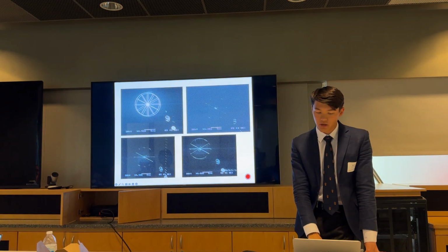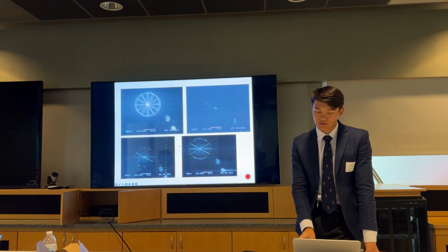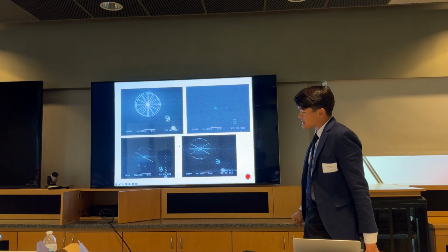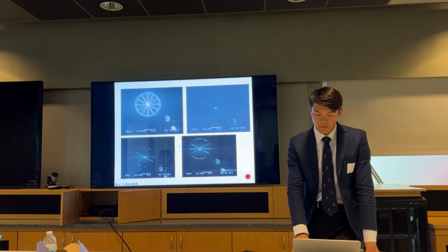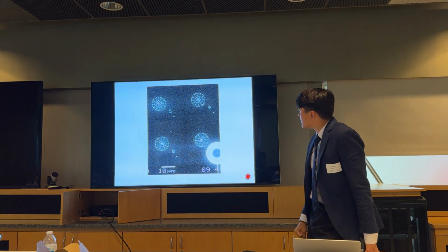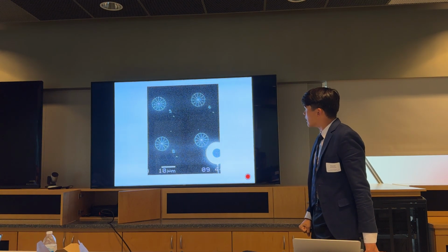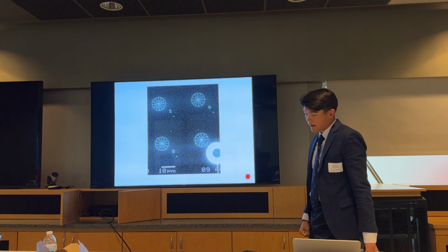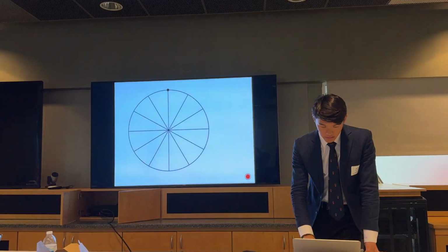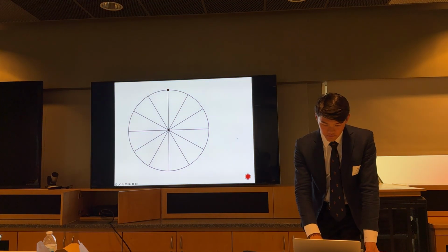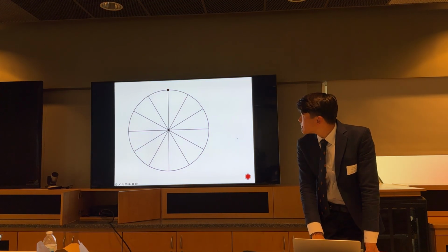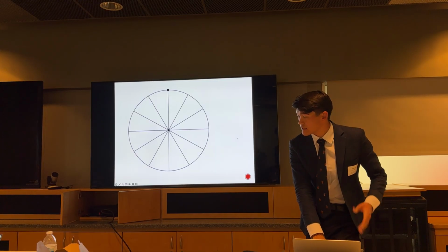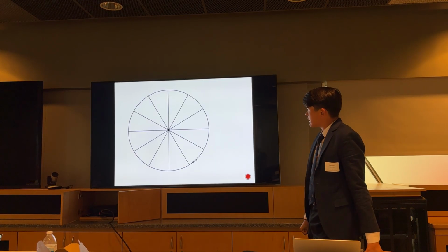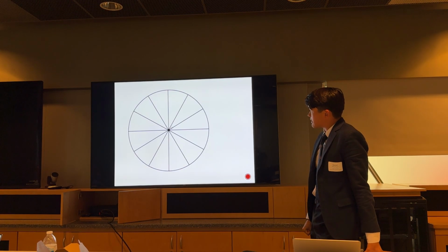I tried increasing the dose, decreasing the dose, all sorts of other things. It seemed like there was this persistent double image. But then it was this image that really gave us a clue of what was likely causing this problem. And I can show a rough animation of what it was like. So here's what's supposed to happen. The black dot shows the desired position of the electron beam, and it goes around and exposes the surface of the PMMA and draws the pattern that we want.